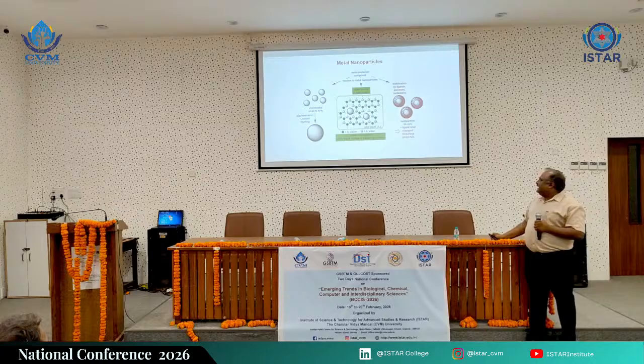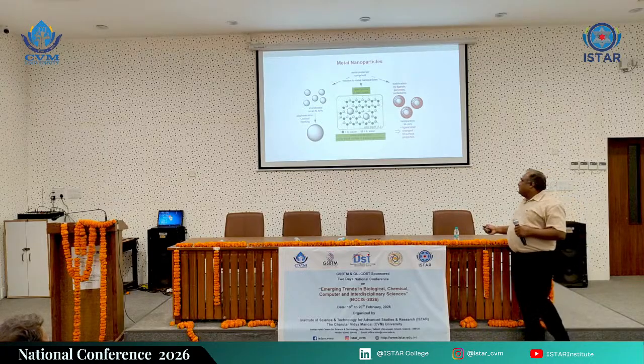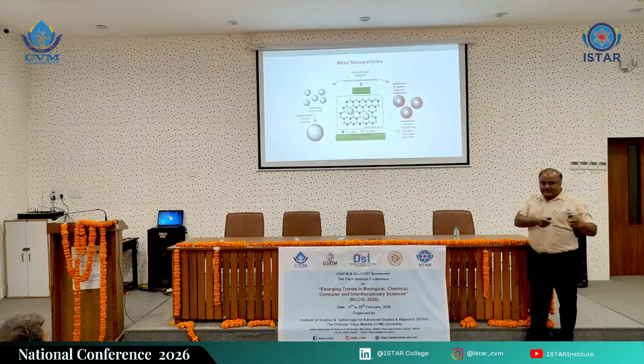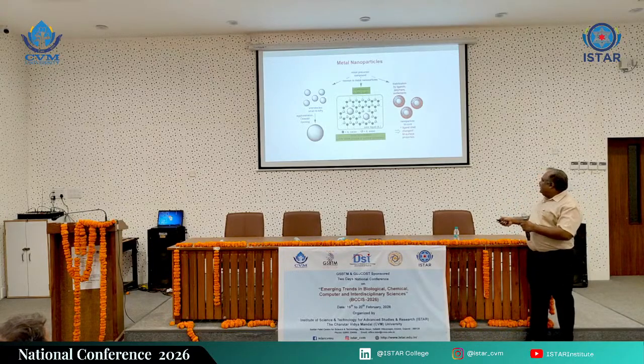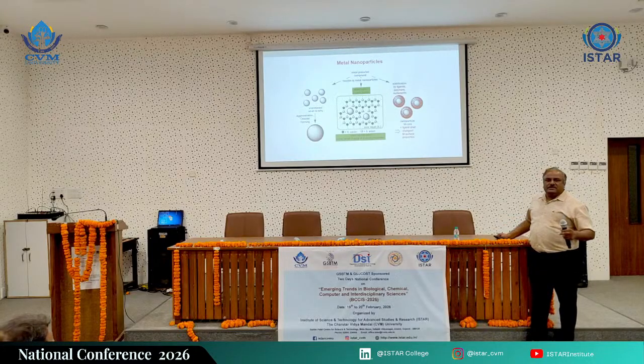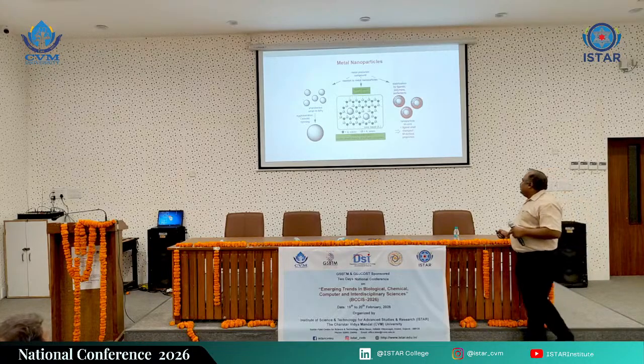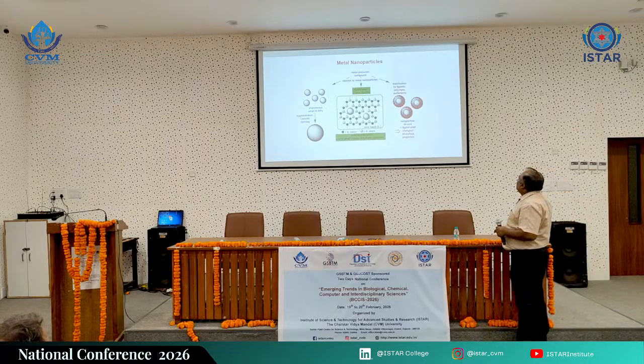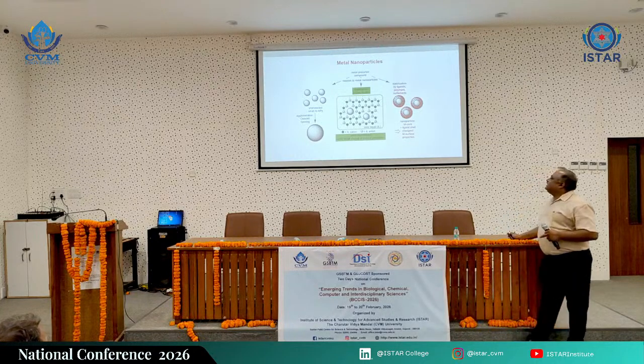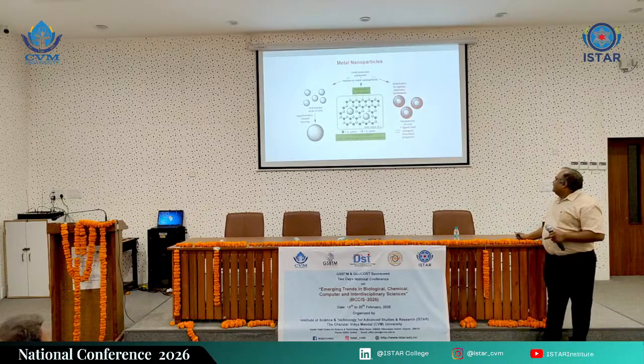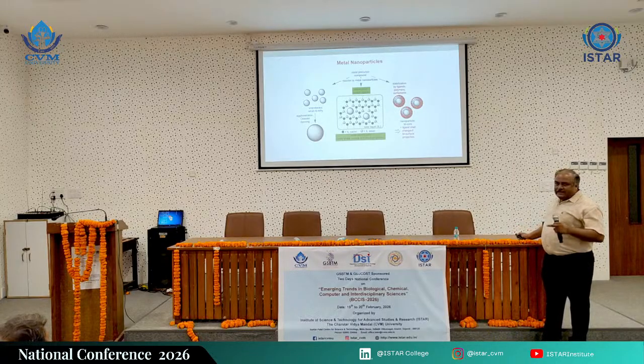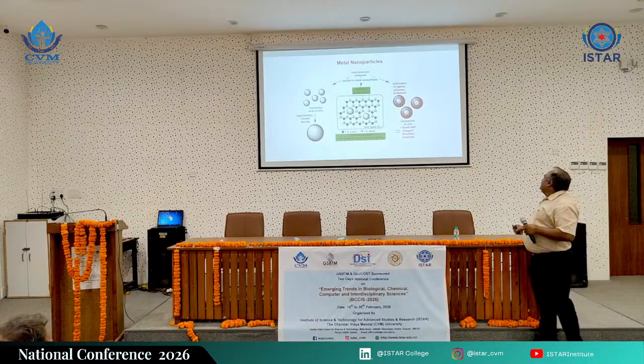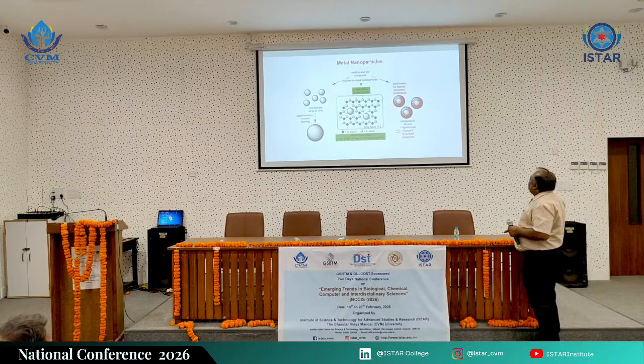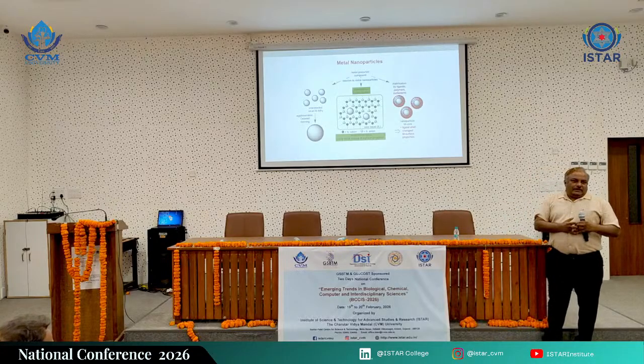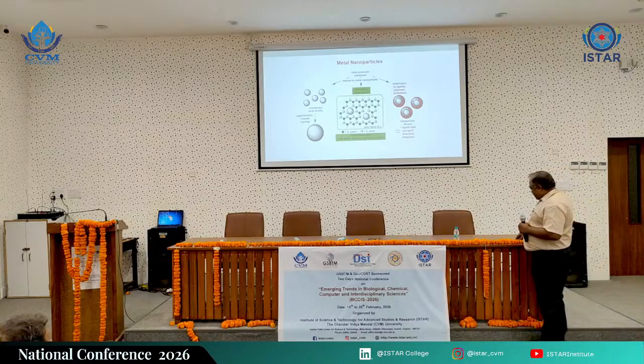Normally, if they are unprotected, they have a tendency to agglomerate, and with Ostwald ripening they might either form clusters or they grow bigger, if only metal nanoparticles are there. If they are metal chalcogenide nanoparticles, then they will form clusters or agglomerates. And to avoid that, normally stabilization is carried out by ligands or polymers or surfactants, which are coated on them. So they are directly suspended into the liquids where these are already there. They will go to the surface and protect. And once their coating happens, they will be practically detached from agglomerates, so they will not agglomerate very quickly.